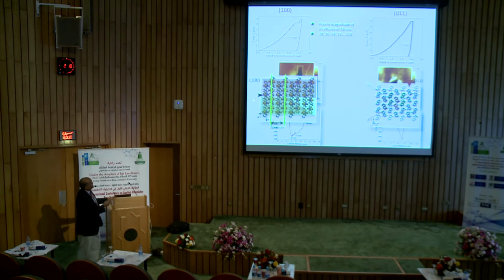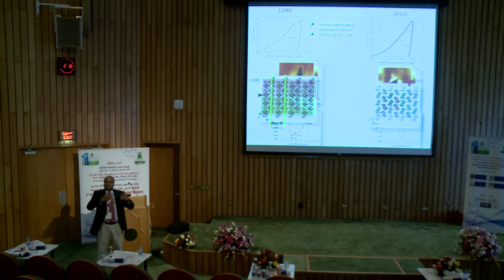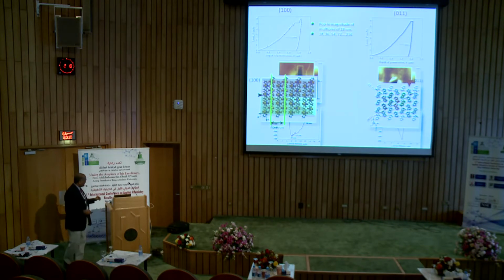But if I, on the other hand, indent on 100, what happens is these slip planes are parallel to this. So these are slip planes, and this is perpendicular to the indentation. So they can't slip like that. So what happens is the stress builds up, and then all of a sudden they release the stress by sliding. So that is why you get these kinds of responses.